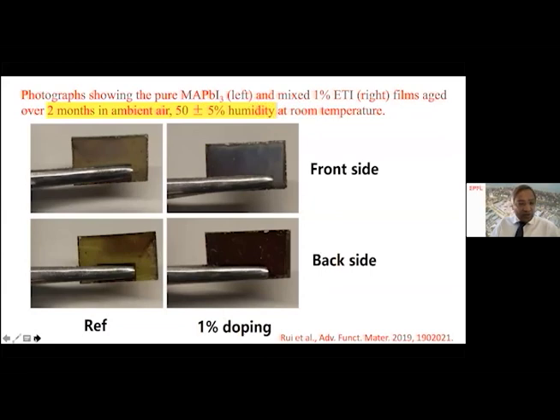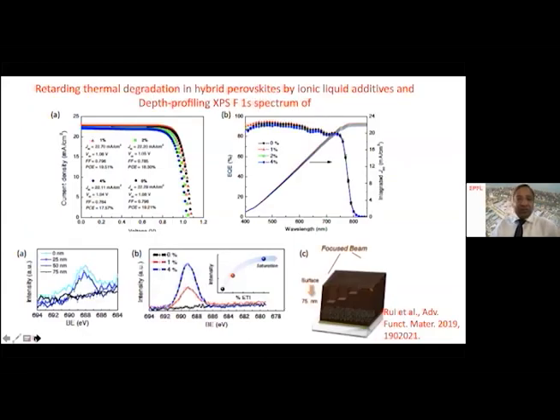And now look at what this ionic liquid is actually doing. So this is the power conversion efficiencies. The reference sample gives you 19% efficiency. With 1%, 19.5% efficiency, with 2% slightly decreasing, 4% is decreasing. But this is the IV characteristics corresponding to IPCE data shown here. But now the question is, what is this ionic liquid doing?